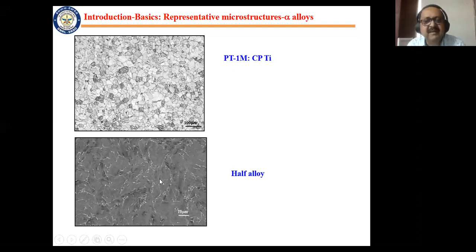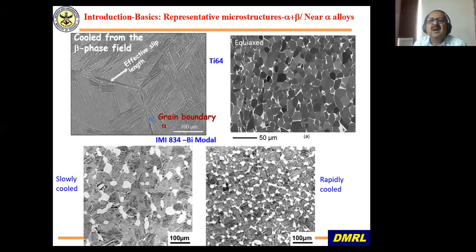Then this is the microstructure of Ti-3Al-2.5V alloy. It is half the composition of Ti-6Al-4V. Here it's also an alpha alloy, but a slight amount of beta is there. So you can see these alpha grains with discontinuous beta phase at the boundaries. The usage of this alloy is very wide, and I'll show you again the usage of these alloys. Then as far as alpha plus beta alloys are concerned, if you heat treat an alpha plus beta alloy like Ti-6Al-4V into the beta phase, and then you have cooled, either air cooled or water quenched.